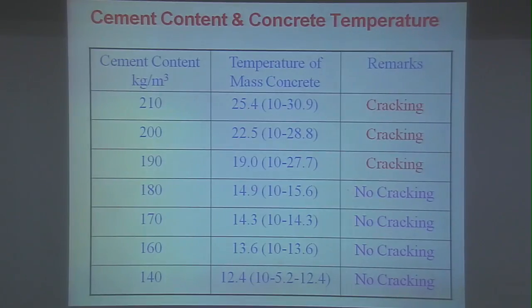And based on this temperature data, we found the cracking in the dam. We knew that this cracking was coming because of the higher cement content in the mass concrete. So we started reducing the cement content in the mass concrete from 210 kg per cubic meter to 140 kg per cubic meter. Up to 190 kg per cubic meter, we were having this cracking in the dam. We were monitoring this data also, and after 180 kg per cubic meter of cement, we were not having any cracking in the dam.